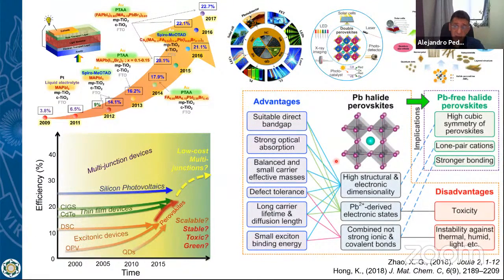It has an advantage. They can be produced very easily, for example, by solvent method, which is much easier than producing a semiconductor solar cell. On the other hand, we still need to solve some instability problems because they are very sensitive to humidity, light, temperature. And the most efficient one used to be based on lead. And you know that lead is not ecologically friendly, and there is a lot of work to get rid of the lead.